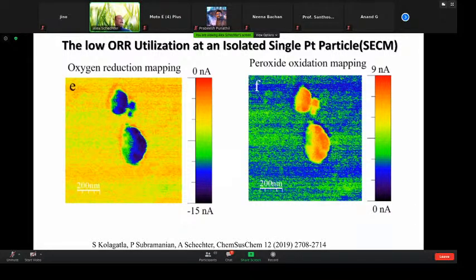Now, if you remember, we have said at the beginning that the reaction on platinum surfaces is agreed by everyone that it is a 4-electron reaction, meaning a direct oxygen going into water. Now, if this is the case, then we should have seen much smaller values of peroxide. We should see 0 value of peroxide. But bear in mind that here we're seeing most of the current goes through the hydrogen peroxide formation pathway, not through the oxygen reduction pathway. And this is counter to what everyone else believes in for a very long time.